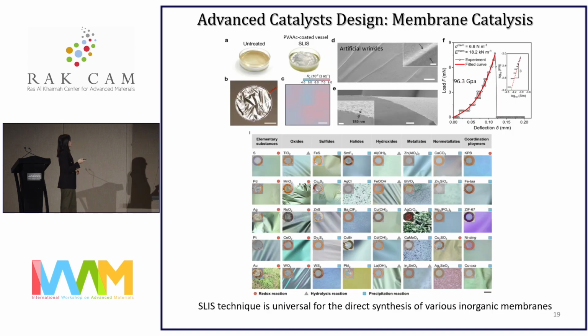So here I'd like to show you the pilot testing of the SLIS reaction on the proposed SLIS mechanism on the PVAc coated vessel. As you can see, a piece of freestanding silver as well as continuous membrane can be obtained right on the liquid surface. And this conductivity measurement shows its structural homogeneity in terms of morphology, density, and thickness on a macro scale, and on a nanoscale or microscale, homogeneity can be confirmed using the scanning electron microscope.